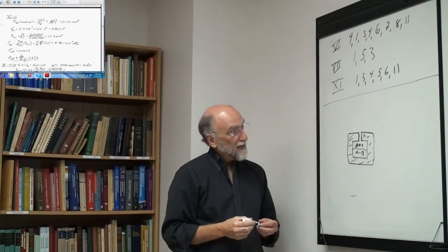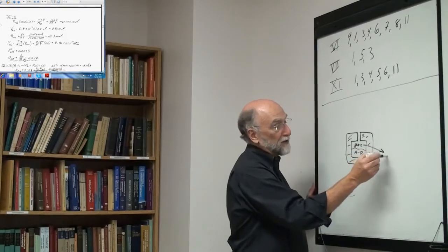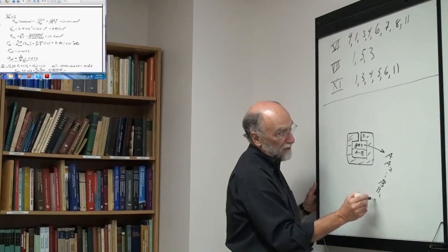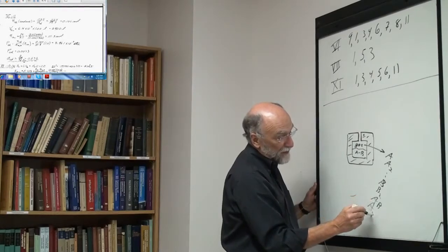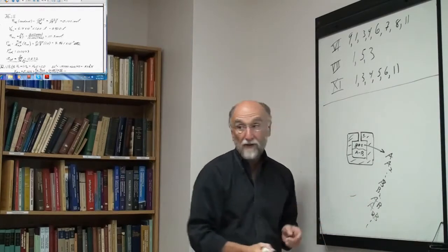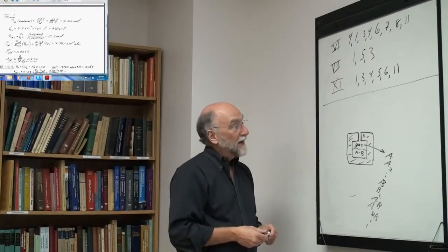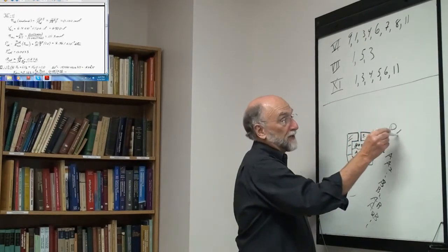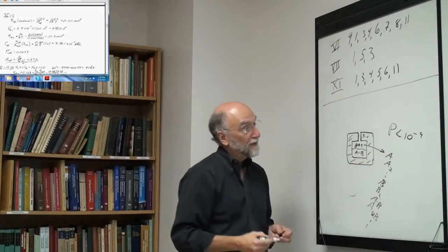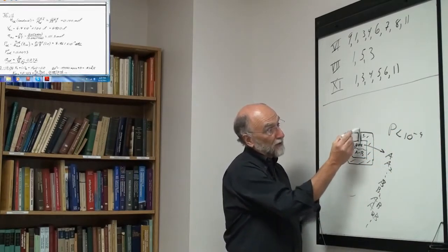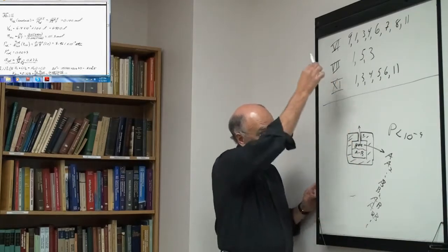And in the gas you will have various molecules. You'll have A, A2, whatever. You'll have B, you'll have B2, you'll have AB, you'll have A2B. These are gaseous molecules in the gas phase, all at equilibrium. They're all in the vapor pressure equilibrium. And they're at very low pressure, say less than 10 to the minus 9, something like that. So the gas is very dilute, so from time to time a gas molecule will go out through the hole.